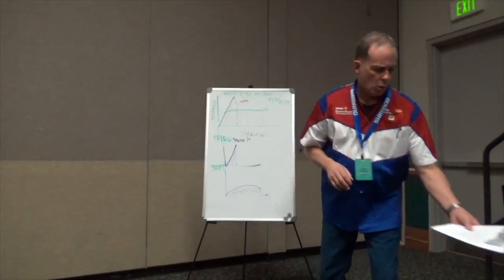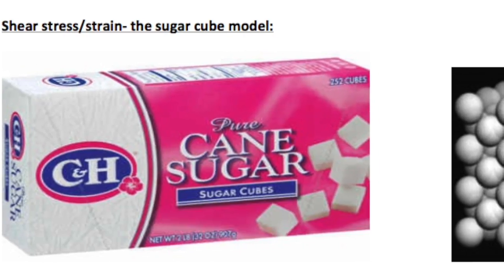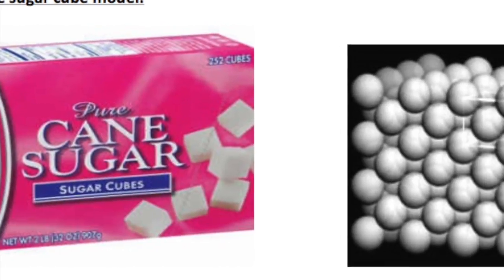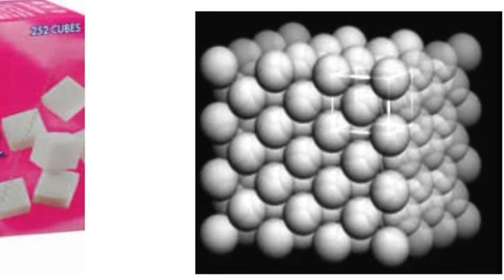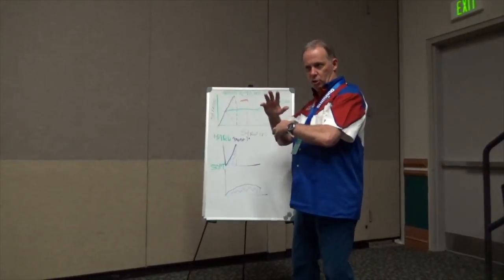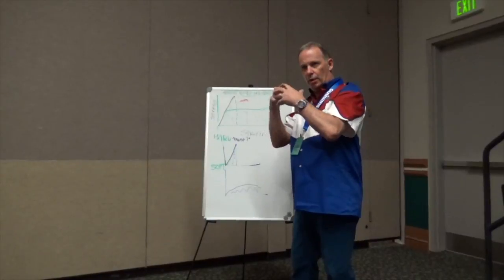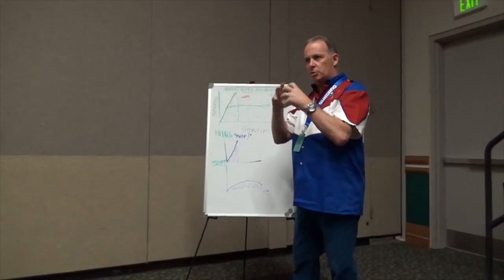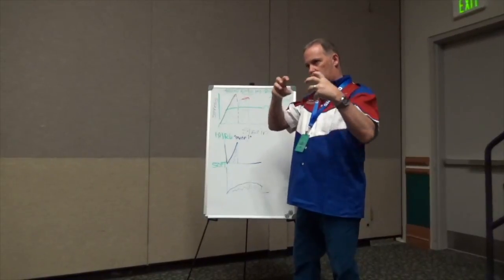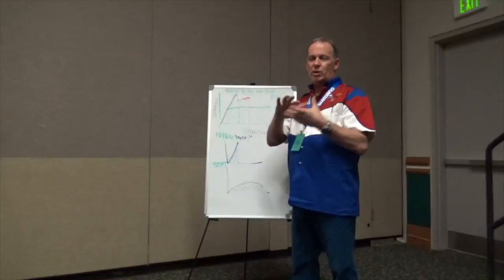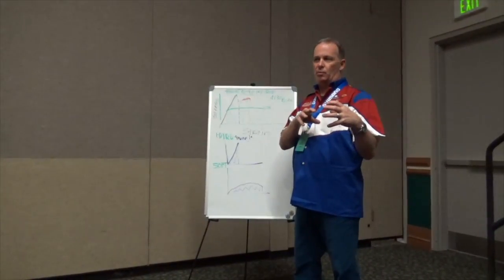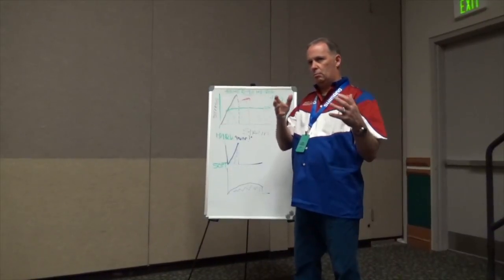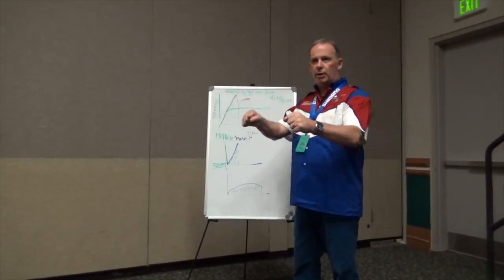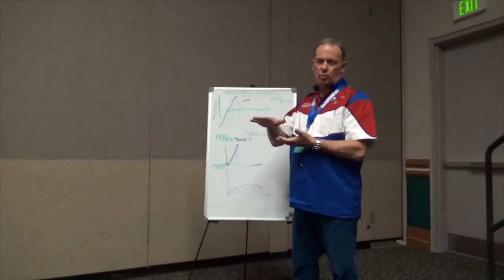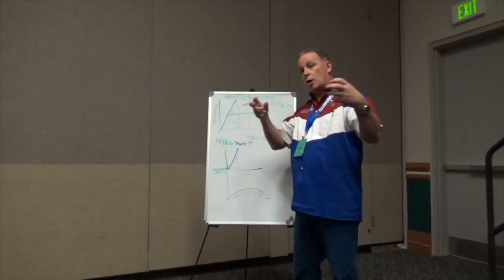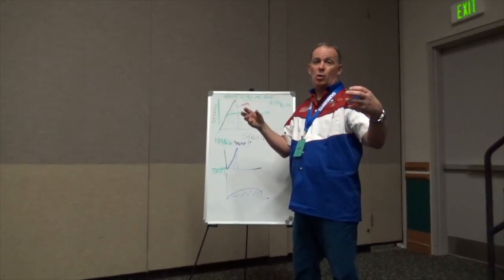I want to talk a little bit about work hardening and heat treating and how they're kind of similar. It's just a different way of getting to a similar result. When you work harden material, as you are pushing those sugar cubes, as they get to where they don't align really well and they start to block each other, those bonds start to go into compression in some places and in tension in others. So those bonds have stored energy. That's where the additional strength comes from, whether it's a cold worked aluminum or a cold worked steel. It doesn't matter. If you roll it enough, you can do some grain refinement, but actually work harden it as well. If you draw it the way we make butted tubes for frames, that work hardens it too.